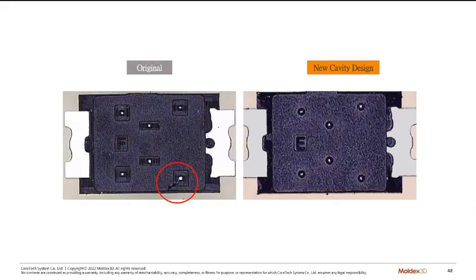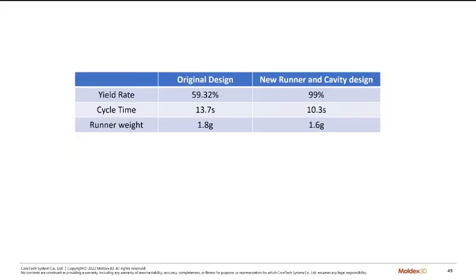Okay, and they actually try it, and in the original design they have a crack here, and with the new design it's good. And they also do the test of the ink. They drop the inks in here, but all of them are fine. So after they improve the runner and the cavities, and when they check it, almost 99% of cavities passed the testing.